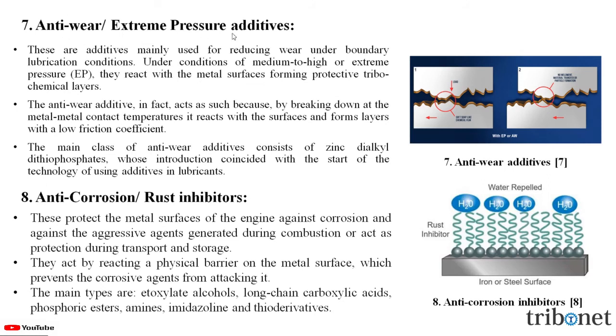The sixth type is anti-wear and extreme pressure additives. These are additives mainly used for reducing wear under boundary lubricated conditions. Under conditions of medium to high or extreme pressure, they react with the metal surfaces forming protective tribochemical layers. The anti-wear additive acts as such because, by breaking down at the metal-metal contact temperature, it reacts with the surfaces and forms layers with a lower friction coefficient. The main class of anti-wear additives consists of zinc dialkyl dithiophosphates, whose introduction coincided with the start of the technology of using additives in lubricants.